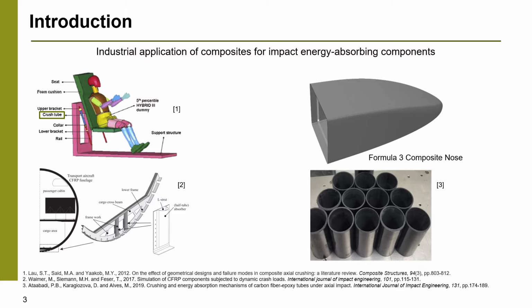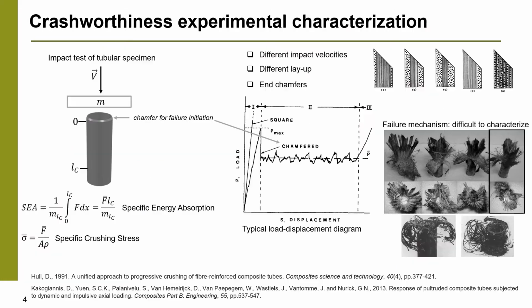To characterize dynamical properties of the material, a special test should be conducted. Here is an example of tubular specimens which are frequently used for material rate characterization. Here is a typical experimental setup for strain rate characterization of composite material. It's based on a tubular specimen subjected to impact of a falling mass, or fixed to that falling mass. The specimen has a chamfered end, which is important for correct failure initiation. The general characteristics obtained from this test are specific energy absorption, with the meaning of force averaged over crushing distance, and another characteristic is specific crushing stress.